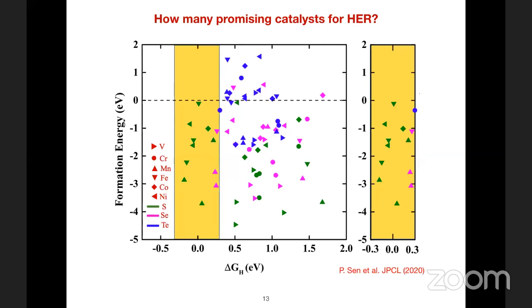All right, so here is a pictorial depiction of what we have found. Each point here is one of these compounds. The colors indicate which chalcogen they contain, and the shape of the symbol tells you which metal atom it contains, on the delta GH versus formation energy plane. So we will be interested in compounds that are below formation energy of 0, and we choose this small window of minus 0.3 to 0.3 eV for delta GH to find out which materials could be promising catalysts. And that is blown up on the right.